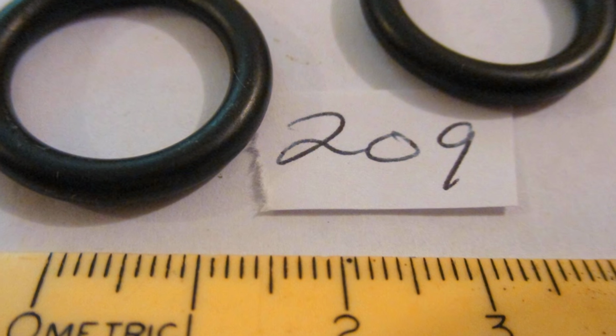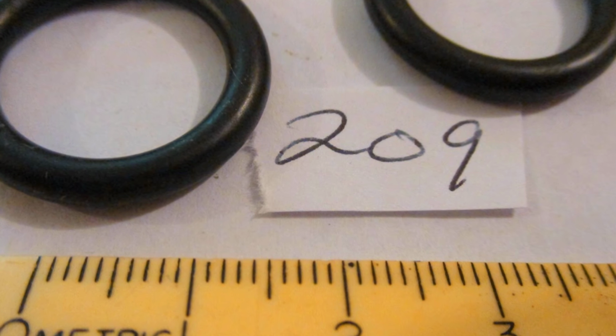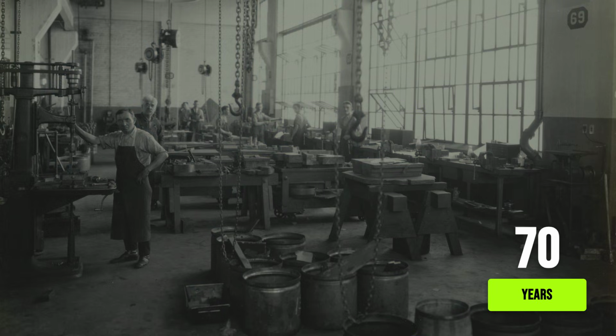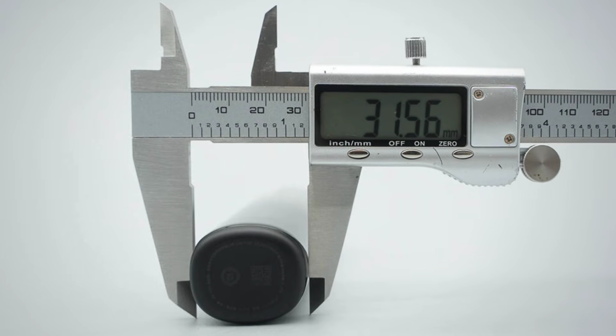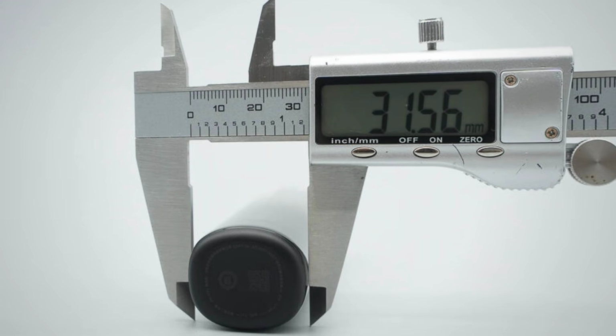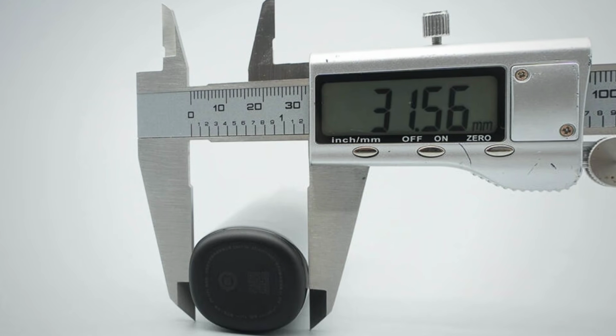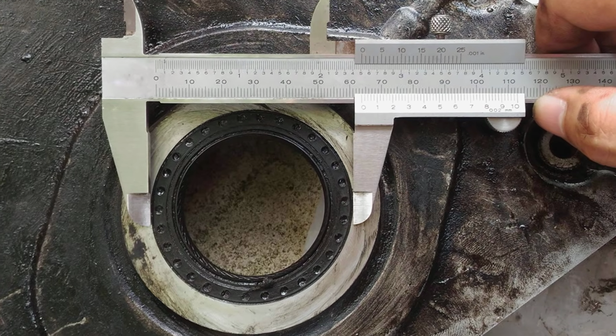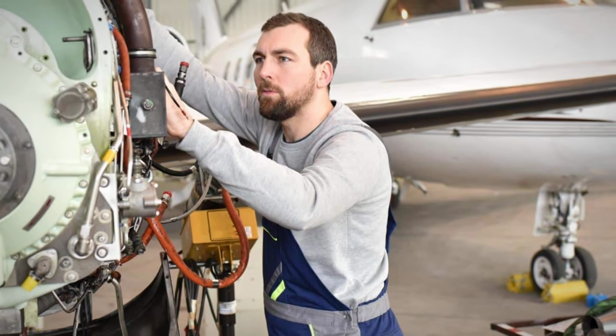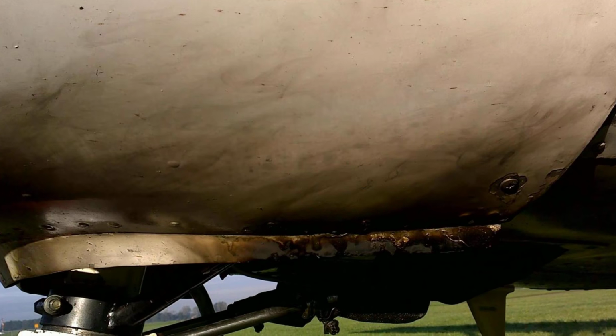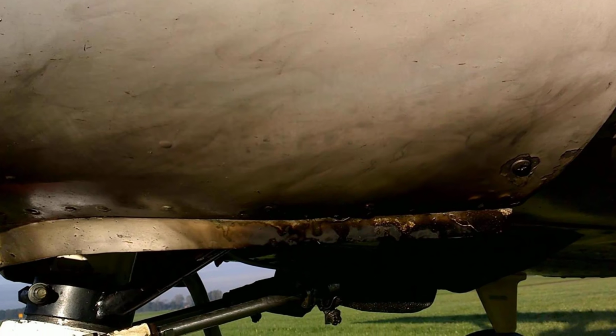G100UL, with its aggressive aromatic backbone, takes Buna N and nitrile, those black rubber rings pressed into service since Eisenhower was president, and swells them by 63%. Not a typo. 63, compared to 4% in 100UL. That is not just a number, that is a control cable refusing to move, a selector valve stuck mid-flight, a fuel leak pooling under the wing.